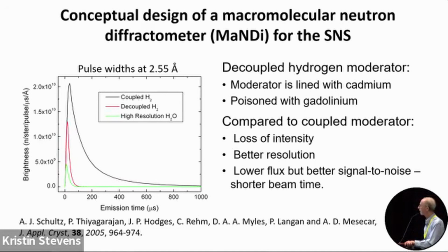The thing is, and that's shown here. So the red curve shown here is the calculated flux for a decoupled moderator. This is the coupled moderator, which is coupled to the beryllium reflector, and neutrons bounce around a lot. So there's a lot more flux, but most of it's going into background. And also the resolution is just not good if you needed to resolve another peak right next to it. So compared to the coupled moderator, there is a loss of intensity, but there's much better resolution and lower flux, but better signal to noise. And so the end result is, for any sample, the beam time will be shorter.